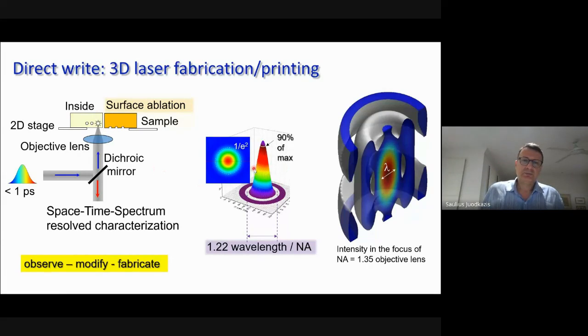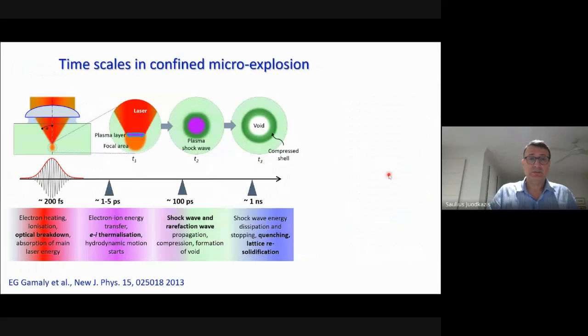If you focus your laser tightly, you can have even higher resolution of modification when you use a stable laser at the very tip of intensity. This is a flat profile of intensity. If we are focusing in the volume, we have an ideal distribution of focal spots shown here. So we can modify material just at the very center, and it can really be sub-wavelength, so there is no problem with breaking the diffraction limit for modification, because it can really be guided only by the high intensity profile.